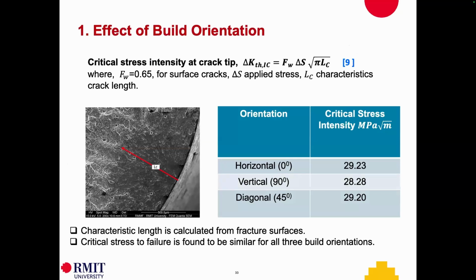We went to the fundamentals and looked at what we call the stress intensity at the crack tip, using this expression with the geometry function, applied stress, and the characteristic length. In our case, the applied stress was the same, and for a surface flaw the geometry factor would be 0.65, so these were the same. We looked at the LC value for each build orientation, and we measured that LC, the critical characteristic length, from the fracture surface, and we found for all three build directions the critical stress is about 29 megapascals. And that explains why we didn't see the effect of 0, 45, and 90-degree builds. That's the understanding we found through fractography analysis.